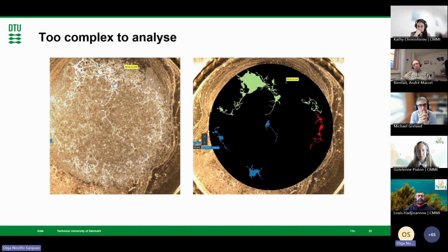And even if it detects, you can see the image on the right is the first scan of the LDIR, because before it takes a scan of the sample, and you can see all these fibers are clumped together and are recognized as one. So here we can see different colors, 1, 2, 3, 4, 5, 6 clumps, but not 6 separate microplastics, really. So we have to be careful with this. Sometimes we get underestimations in our samples because of this issue, but we need to also be careful with overestimation, because if we put a lot of sensitivity in the instrument, the instrument will start detecting artifacts that are not really microplastics, and then we have the risk of overestimation. So it's a balance. It's finding the sweet spot.